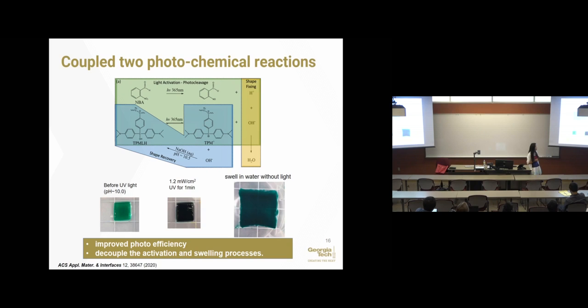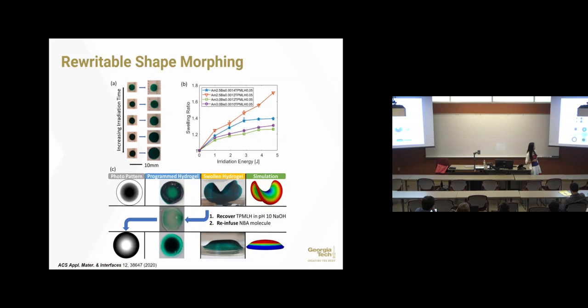For another thing, taking away this product will force the reaction more toward the forward direction, so we can get a higher swelling ratio. You can see here, this is the original gel. After light activation, it looks dark. It is just the molecule changing color. Then we take away the light source, and the material remembers this activation. Then we put it into water, and it swells dramatically. So we can improve the photo efficiency and also decouple the activation and swelling processes.